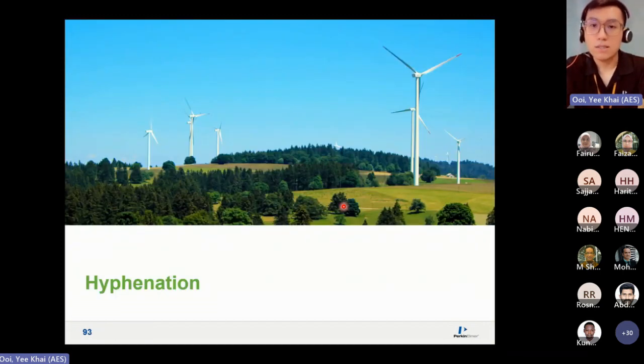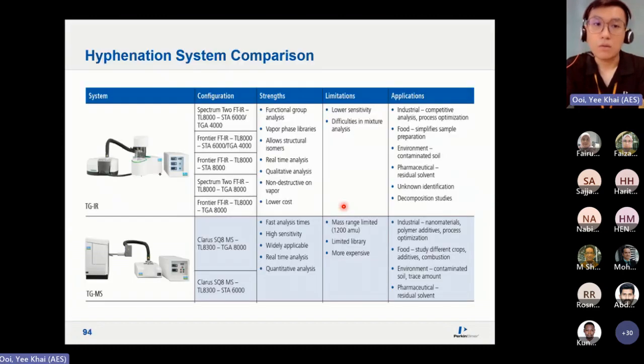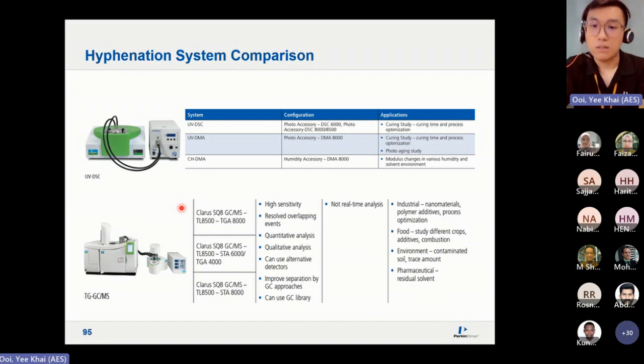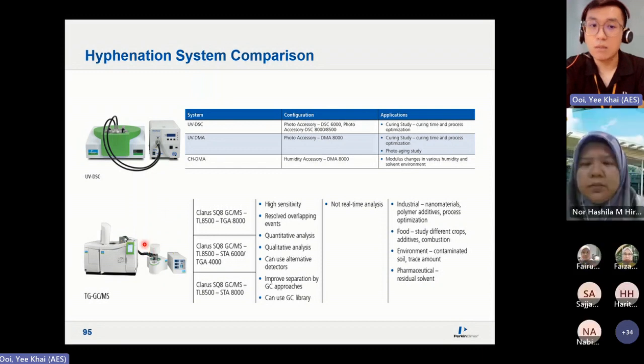The last part will be hyphenation, just some additional information for you. Like what I mentioned just now, we have TG-IR. You can hook it up with TG-MS as well, so any of our TGA, you can do that. TG-IR, TG-MS. This will give you the quantitative results, meaning the weight loss percentages, and the IR or MS or even GC-MS, depending on the detectors that you hook it up with, will give you the qualitative result. Meaning the gases coming from the TGA, you can flow into GC-MS or IR to do identification, based on retention time, mass-to-charge ratio, or even the functional group from the IR spectrum.